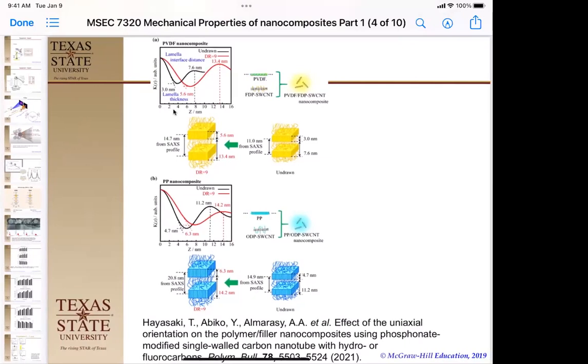So it's drawn out 9 times as long as from the starting point. Okay. But you're saying that the distance between the two is only increased by that certain amount. Right. So the lamellae themselves have gotten slightly larger too, meaning that some of the rubbery polymer is turned into crystalline polymer, and some of the crystalline regimes are a little further apart. So you can almost imagine that you're squeezing mortar in between the bricks as you're doing it.